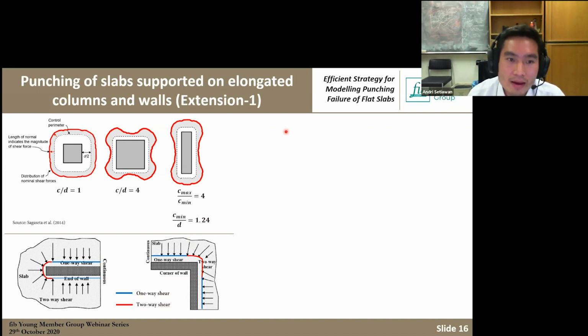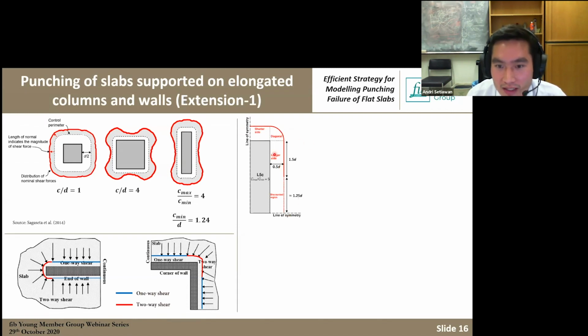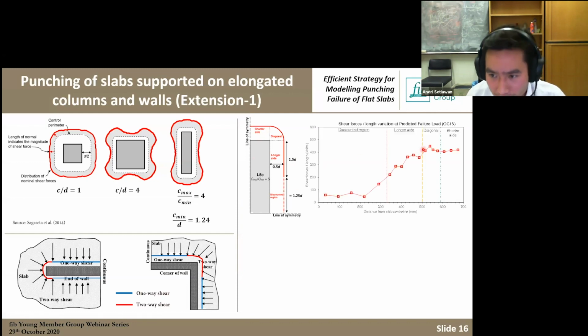So we did some comprehensive 3D solid analysis. I modeled a slab like this with a rectangular column from the real test, and we extracted the variation of shear forces along this control perimeter. We have 4 regions: the shorter side and diagonal, where we expect higher shear stress, and we also have the longer side and the discounted region. The 1.5D that we define in here is compatible with the model code suggestion that if you have a very long column, you need to neglect this region, so that when you consider the resistance to punching, you only consider the 1.5D from the column. So we tried to use this assumption, and actually it matches quite well with the actual distribution.